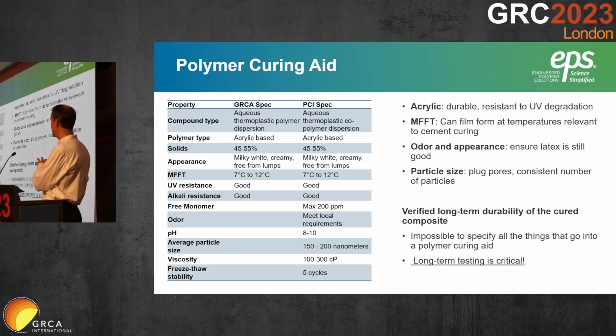Odor, pH 8 to 10, close to the pH of cement. Average particle size, I'll talk more about this later, but the particle size, just keeping things consistent so it does the same thing every time. Particle size controls the number of particles that are in there, and also the size of pores that can be blocked. Viscosity, again, it's just a spec, and freeze thaw stability is in there.